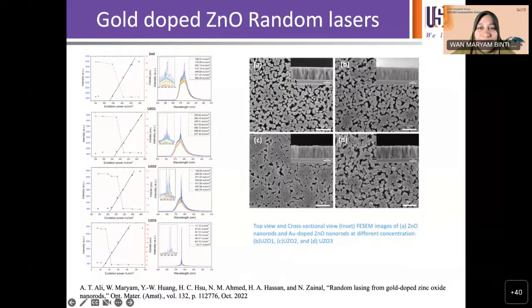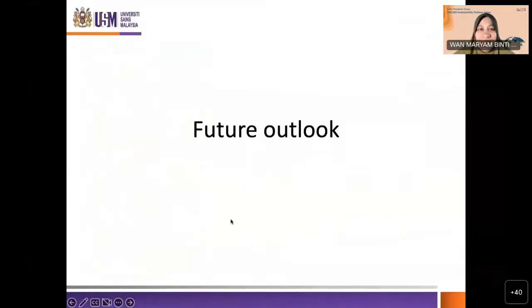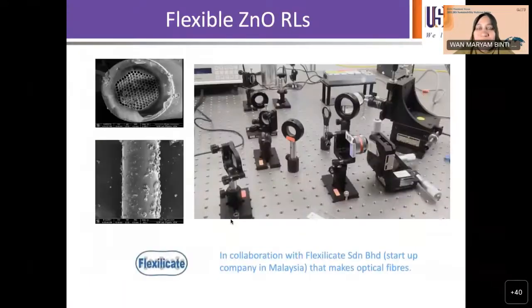So the main thing is we want to maintain this. You see the height here of the nanorods is all maintained at roughly the same height. Changes of that would show other changes that can affect random lasing. So we wanted to make sure that this was fixed, as fixed as possible. And so we were sure that the difference in lasing threshold was actually caused by the doping itself.